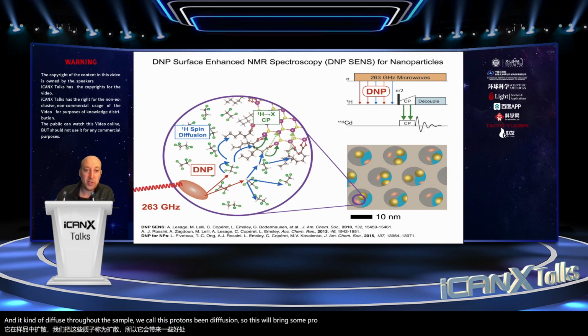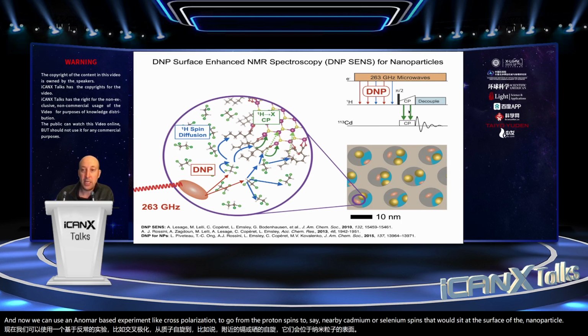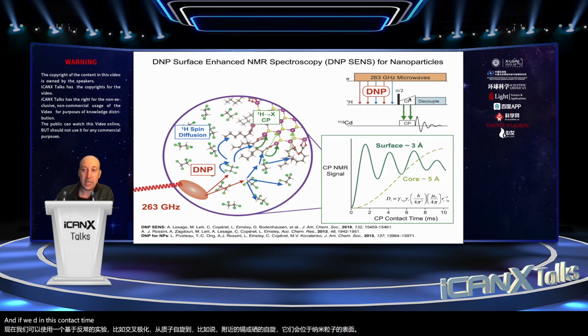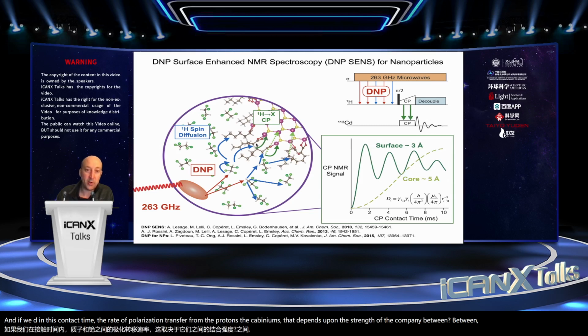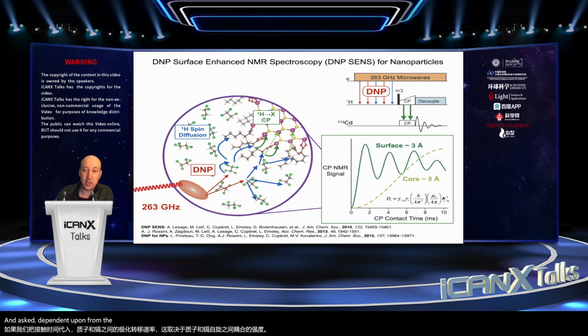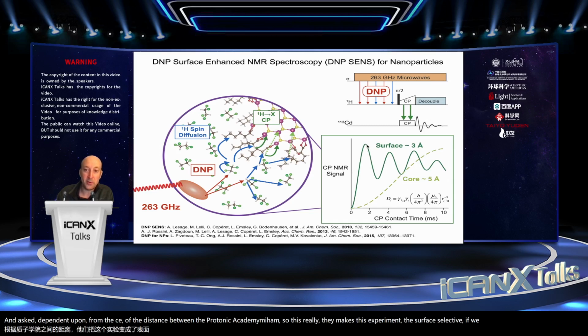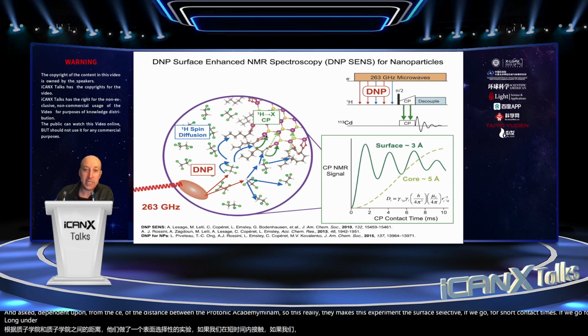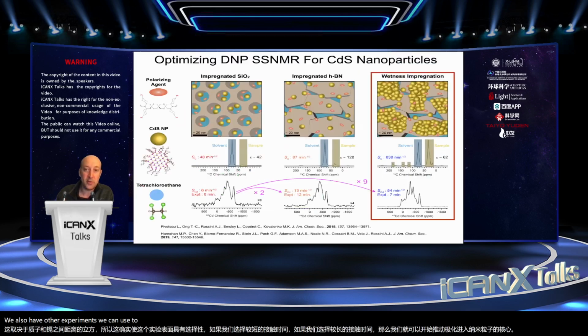So this will bring some proton magnetization to protons nearby to the surface of the nanoparticle. And now we can use an NMR-based experiment like cross-polarization to go from the proton spins to, say, nearby cadmium or selenium spins that would sit at the surface of the nanoparticle. And if we dial in this contact time, the rate of polarization transfer from the protons to the cadmiums depends upon the strength of the coupling between the proton and cadmium spins. And that's dependent upon the cube of the distance between the proton and cadmium. So this really makes this experiment surface selective if we go for short contact times. If we go for longer contact times, then we can start to push the polarization into the core of the nanoparticle. We also have other experiments we can use to do that.